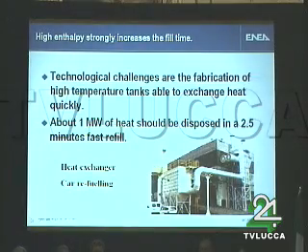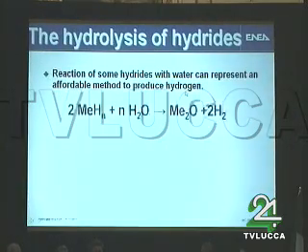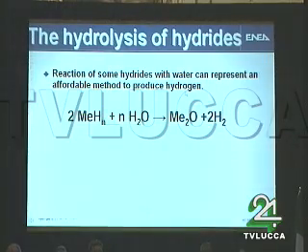Technological challenges are the fabrication of high-temperature tanks working at about 300 degrees, able to exchange heat very quickly. About 1 megawatt of heat should be disposed of in 2.5 minutes for a fast refill. This is a picture showing a car refueling very fast and the heat exchanger in the back to remove the heat.